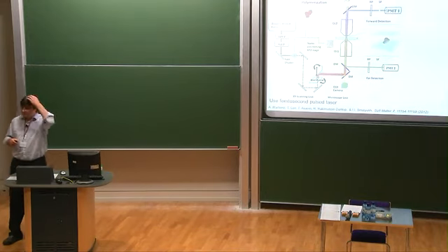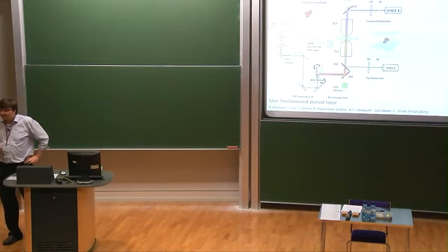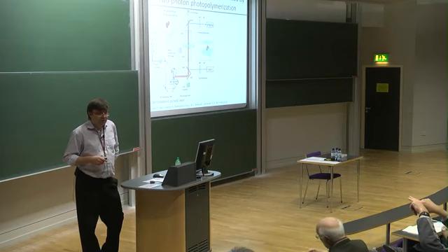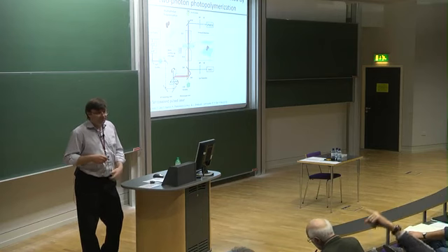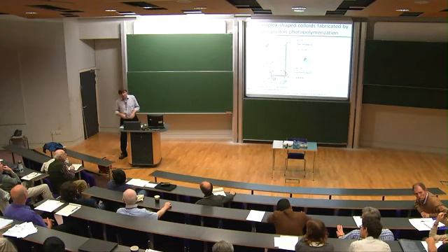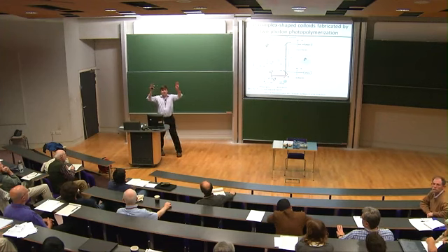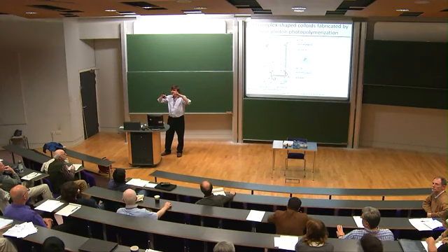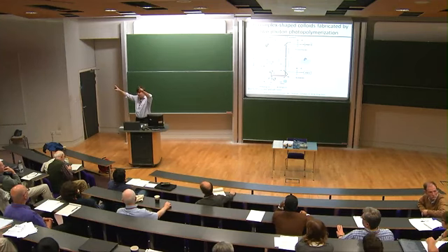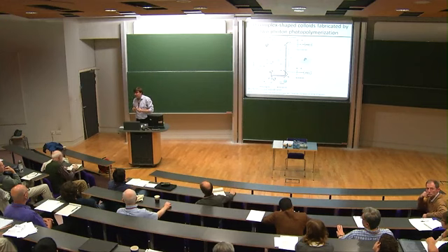In bulk, if you have a +1 disclination line, it's energetically favorable for that to split into two 1/2 lines and for those to separate to infinity. Evidently, that's not true for the boojum. Is there an easy way to understand that? Well, it's because if you would do that, you would induce a lot more distortions. But locally, that's still favorable, right? If you would propagate that to infinity, that would be more distortions. To me, that's an easy way to understand it.